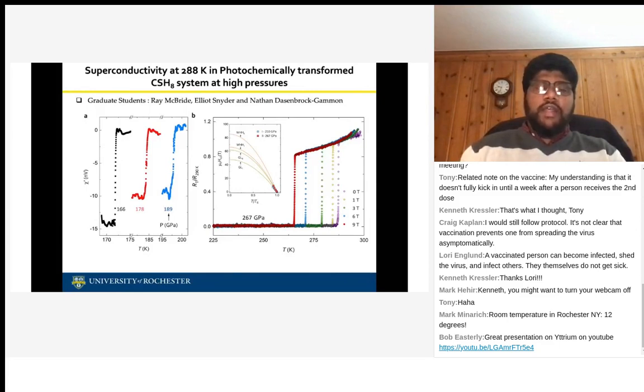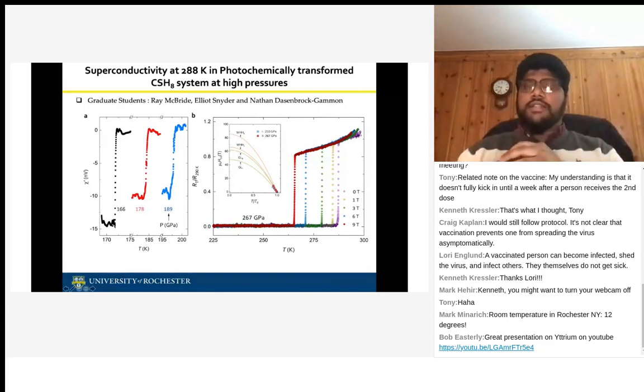This is the signal that you observe: when you go through this transition, you get a negative value of this magnetic susceptibility, indicating it's a diamagnetic transition. And then also, when you apply a magnetic field, since magnetic fields are not really a friend of superconductivity, it destroys the superconductivity in general. So you see the suppression of the transition temperature to lower temperature, which indicates a superconducting material.